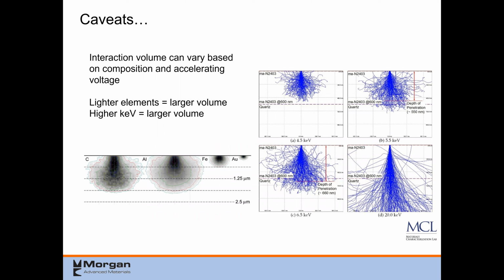The interaction volume varies depending upon what the material is that you're looking at and also the accelerating voltage you use. Lighter elements tend to have a larger volume. So with things like carbon and aluminum, you get this huge interaction volume, whereas something like gold or silver has very little interaction volume, so you're getting it from closer to the surface. Likewise, if you increase your accelerating voltage, you're going to get deeper into the material. So if you're looking at thin films, lower accelerating voltage is better so that you only get the thin film rather than getting into the substrate.